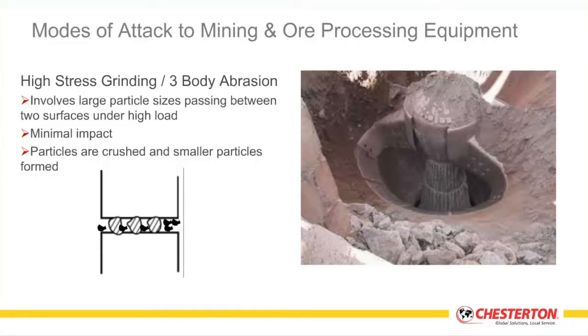ball mills. There may be some impact, but it would be limited to a localized area. It occurs when particles are crushed between two surfaces and you are liberating smaller and smaller particle sizes. So you're continuously exposing new sharp edges that can cut, grind, and damage the base metal.